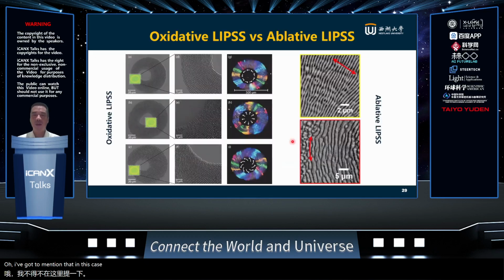And all these gratings have a period similar to the incident wavelength. We are using a 1030 nanometer wavelength femtosecond laser, and the period here is around 900 to 1000 nanometers, depending on the thickness of the substrate. Oh, I forgot to mention that in this case, we grow these gratings on a very thin layer of silicon on top of oxide. This silicon is on the order of tens to a few hundred nanometers, on silicon dioxide.